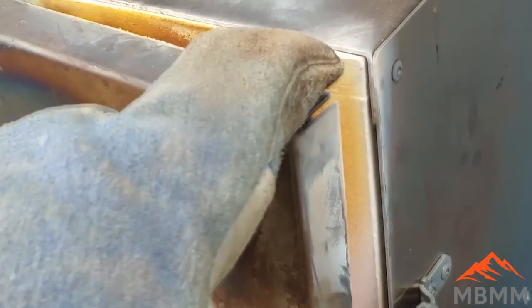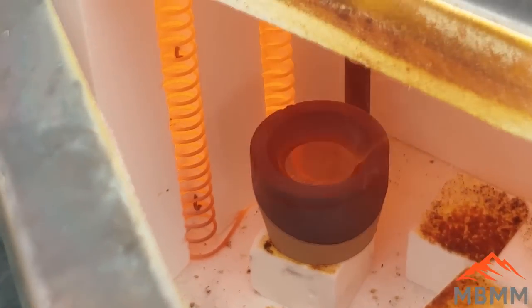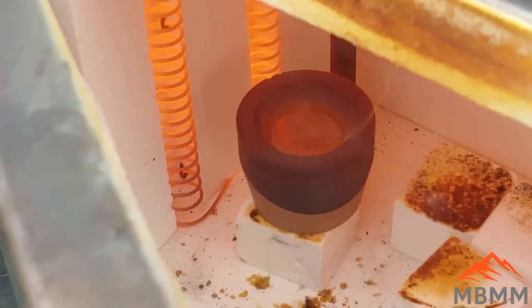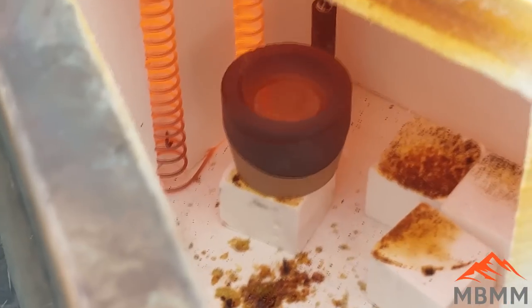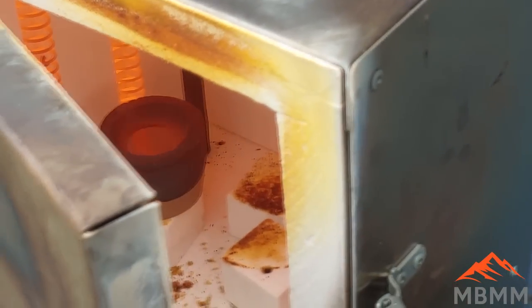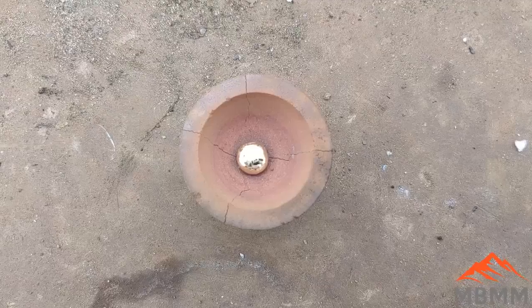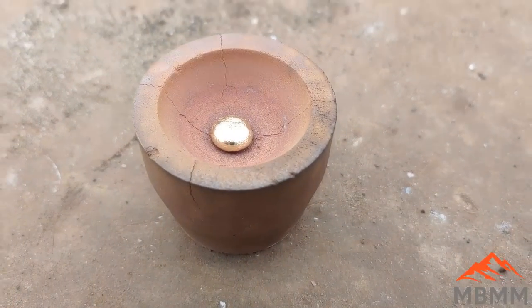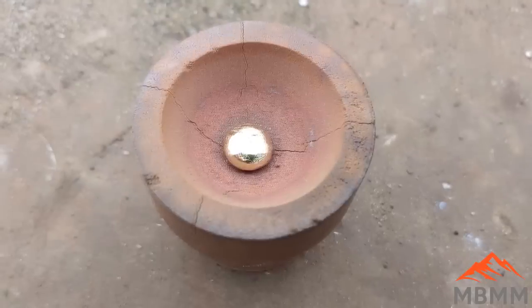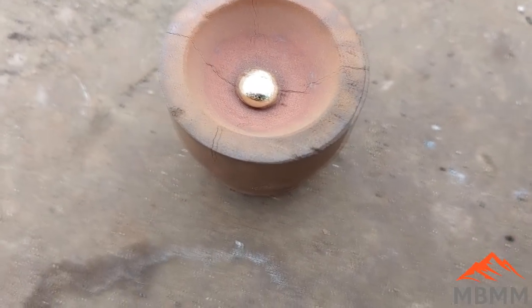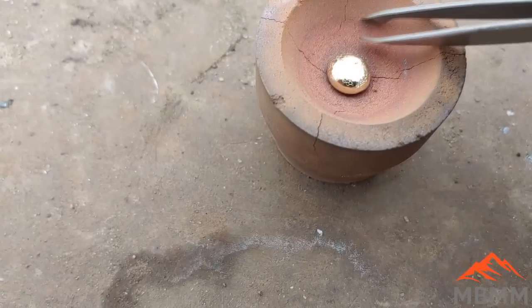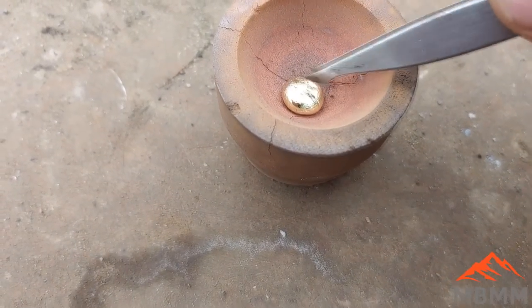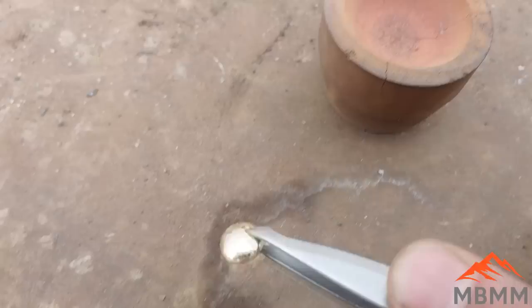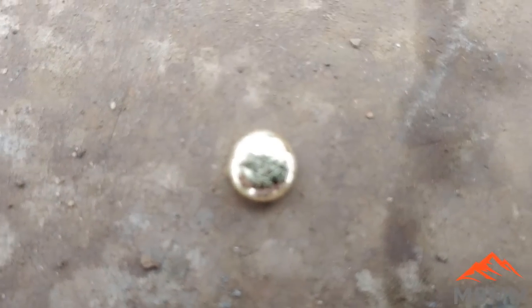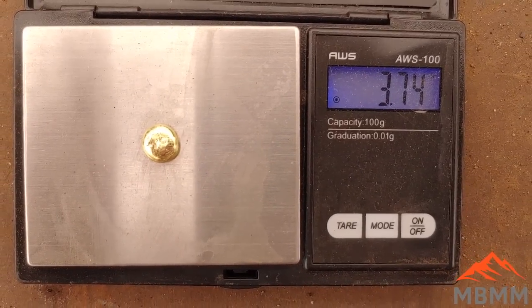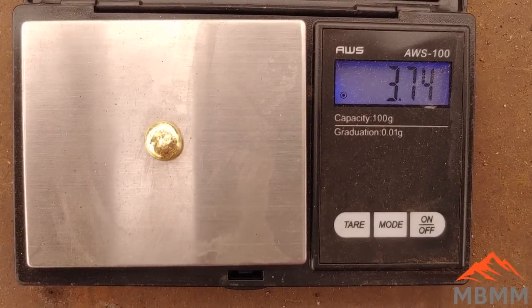This is our lead block from number 1. And I don't know if you can see there, but the lead oxide's molten and it's kind of running over into the cupel. So let that go and hopefully get a little gold bead when we're done. All right, here's our gold from the number 1. Nice little button there. It's still smoking hot, but let me see if I can do this and video at the same time. It shouldn't be attached to the cupel. It should just pop out of there. Yeah. So there's our gold bead. And there you go. Our bead's cooled down, and just from the number 1, we got 3.74 grams.